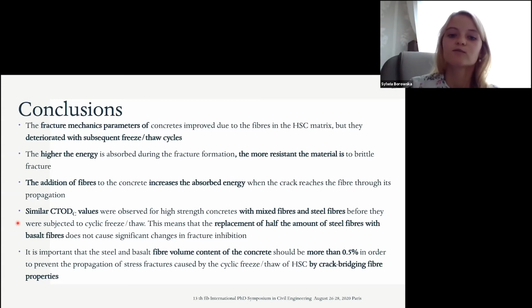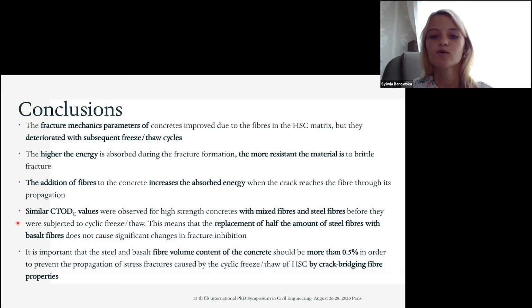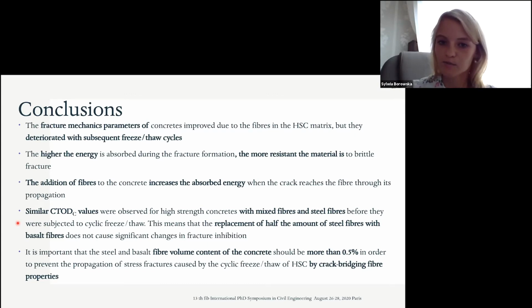Similar critical crack tip opening displacement values were observed for high-strength concrete with mixed fibers and steel fibers before they were subjected to freeze-thaw. This means that the replacement of half the amount of steel fibers with basalt fibers doesn't cause significant change in fracture inhibition. It's important that the steel and basalt fiber volume content of the concrete should be more than 0.5% in order to prevent the propagation of stress fractures caused by the freeze-thaw cycling of high-strength concrete by crack-bridging fiber properties. The frost resistance of high-strength concrete is associated with absorbability.